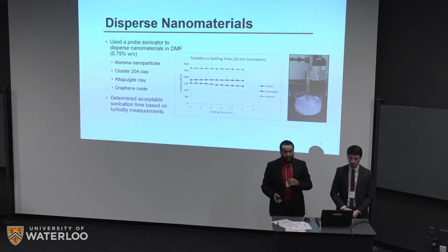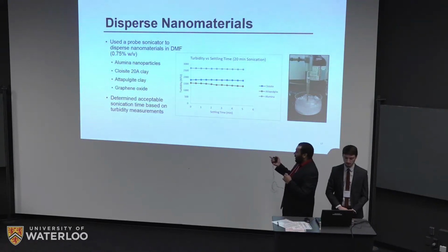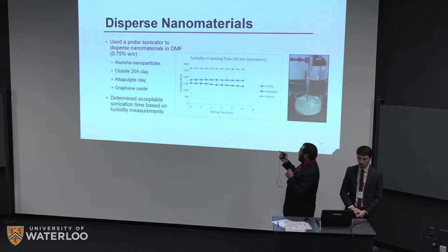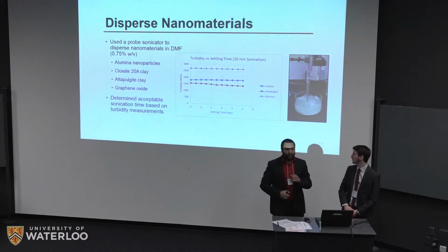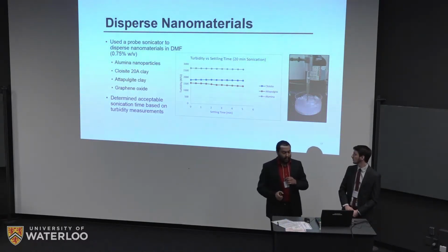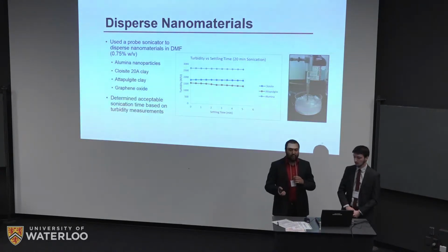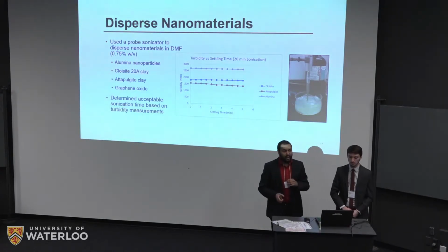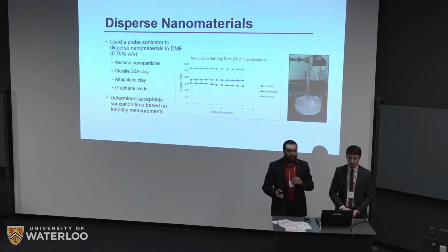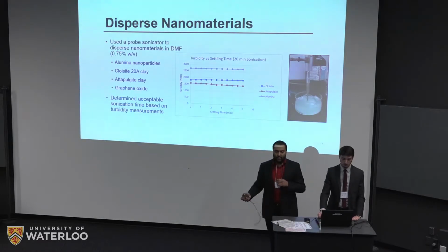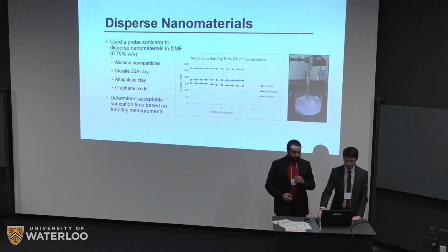As you can see on the graph here, at 20-minute pulse sonication, the cloisite, attapulgite, and alumina all showed very good stability. We weren't able to measure graphene oxide directly because it interfered with the turbidity measurement, but we figured it will follow the same trend as these materials, and so we used 20-minute sonication across the board.